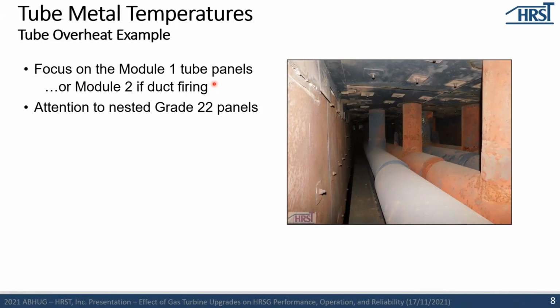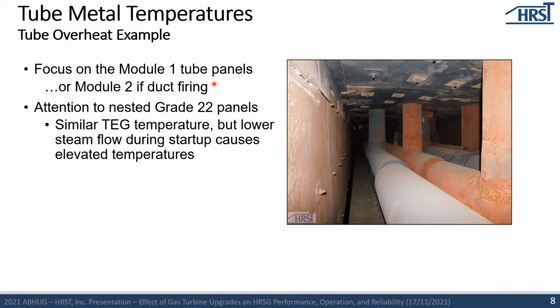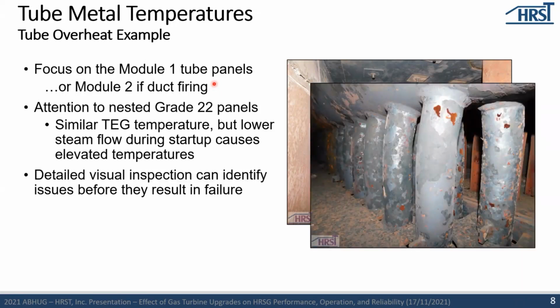superheater or reheater panels. And the reason that these tend to gain a lot of attention is because the exhaust gas temperature at those locations is very similar to what the grade 91 material is experiencing. But during startup or low load cases, the flow through the reheat system is notably lower. So this increases the tube metal temperatures and the header metal temperatures at these locations. So one of the best ways to look at this is just do a detailed visual inspection to identify if there's any issues that are occurring.